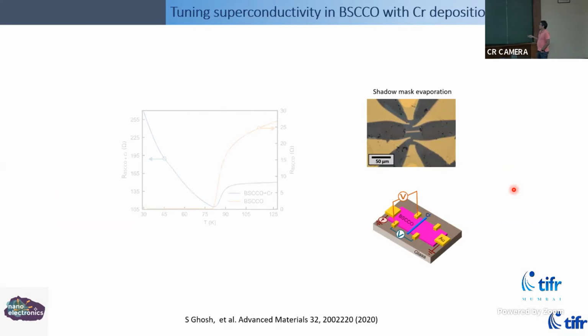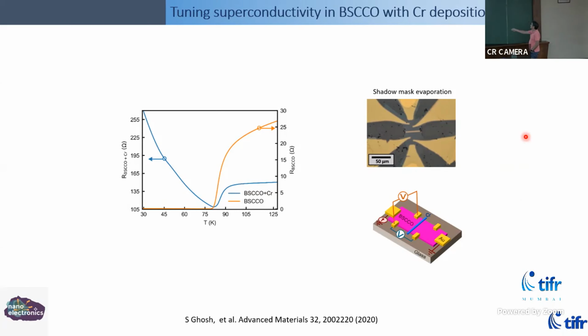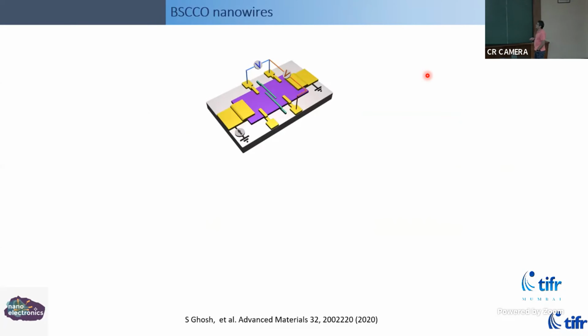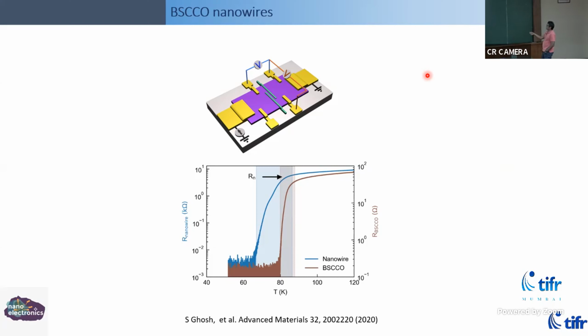So this was sort of our demonstration. Here, for example, in this image, this is a very thin sheet of this high temperature superconductor with electrical connections of gold. And if you put this ribbon in between, which is of chromium, it basically makes that whole layer of superconductor insulating. And that was a very interesting and serendipitous discovery that we made, that you don't really need to cut it, because these materials are extremely sensitive to oxygen stoichiometry. Like a rangoli, you drop the chromium on top, and that completely disrupts the superconductivity underneath. And that sort of idea is what we have pushed to make these kind of devices. So for demonstration, what we do is we can make 10 micron long or longer.